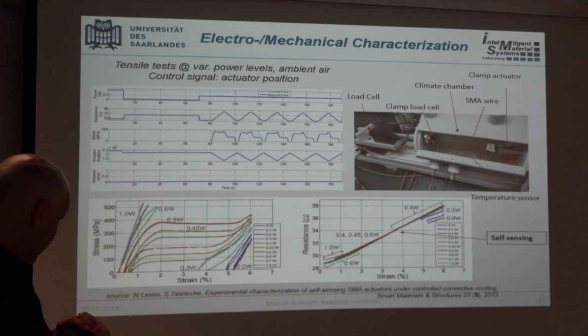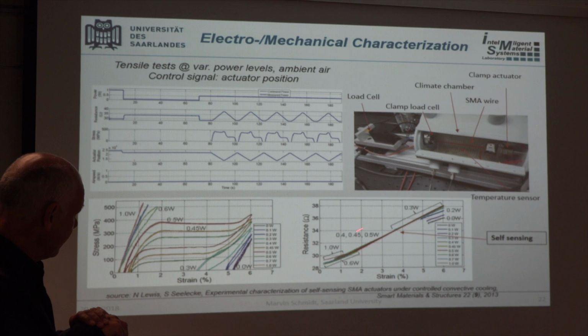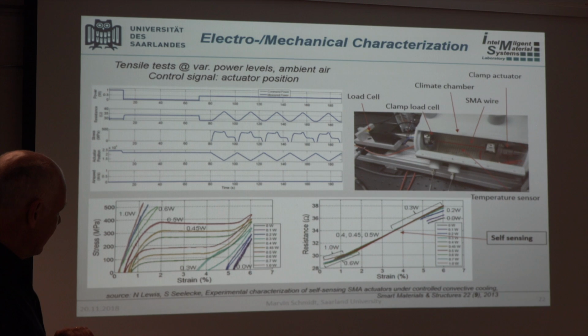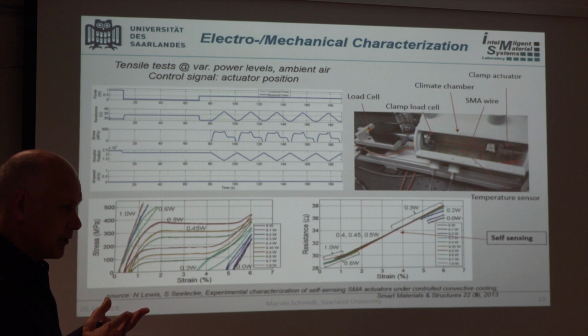What's also very interesting is if during that very same experiment you also record the electric resistance, and this is shown here. And you see a lot of interesting things from the resistance behavior. If you look at the electrical resistance, what is it? Resistivity times length divided by cross-sectional area, right? So there are 3 mechanisms in the resistance that basically contribute to change. And you can all see them in this diagram.